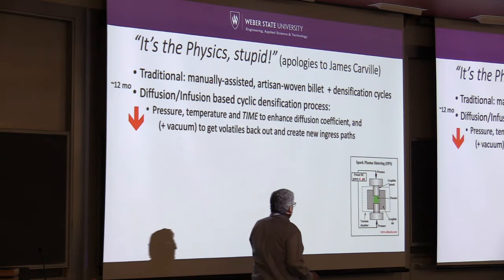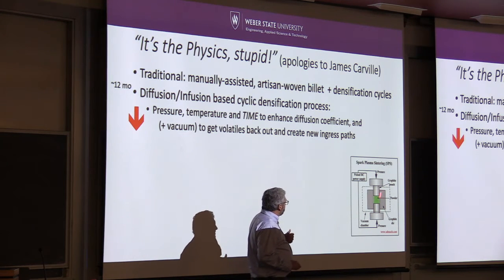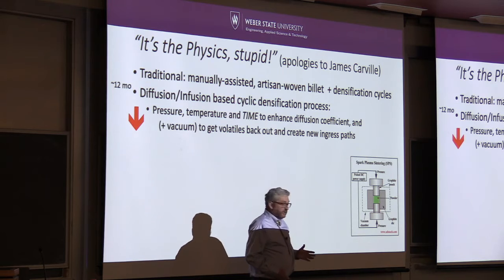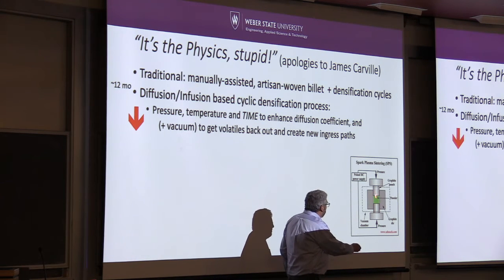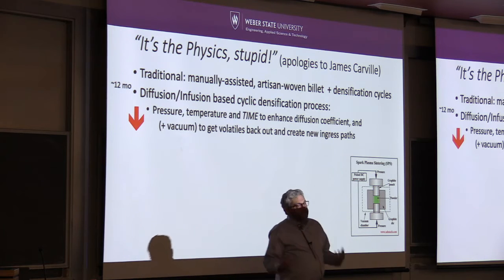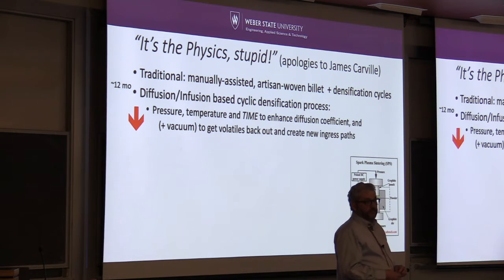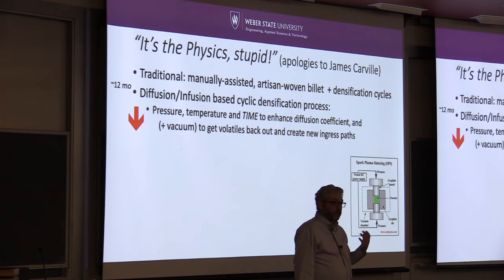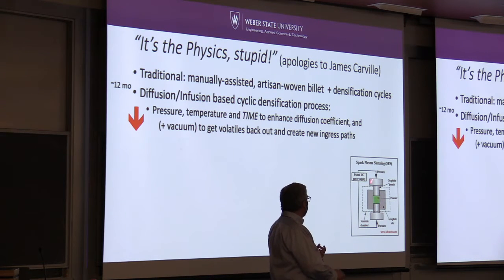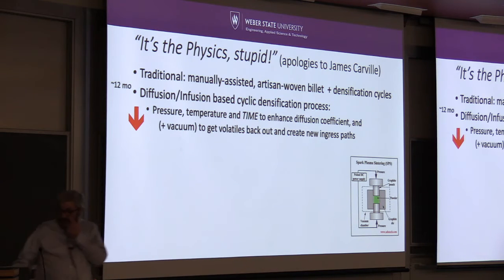The idea behind it is that you have a die set forcing DC current through the sample under pressure, with direct heating, and then you can rapidly sinter the part. Okay, so you're probably familiar with hot isostatic pressing. This is similar, except that you're directly heating the sample with I squared R heating. You dump a whole bunch of current through the sample, it self-heats, and you get uniform, rapid heating and cooling, and when you're done, you've got a very, very nice compact, high density.